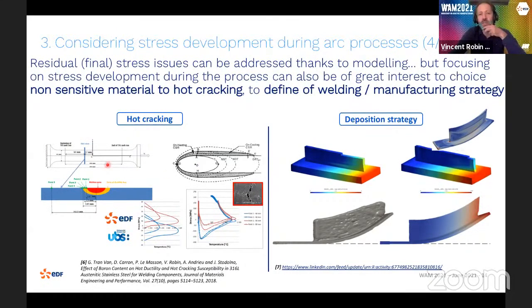We have developed a specific weldability test for which we can modify the external constraint so that it represents a realistic weld configuration. And you can notice that the behavior in the heat affected zone is always the same: compression at heating, and tensile stress at cooling. But when you apply some extra constraint on the material, then you can activate the sensitivity of the material to hot cracking. You can see in the curve in red that making the constraint higher during cooling leads to a level of stress at the temperature where liquefaction occurs, leading to cracks. So this is also a way to calibrate models in order to prevent the risk of cracking for welding applications.